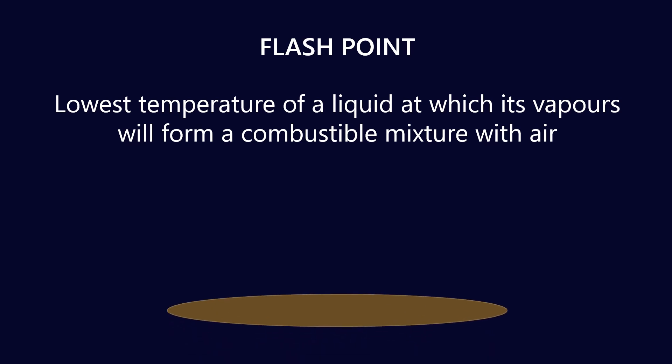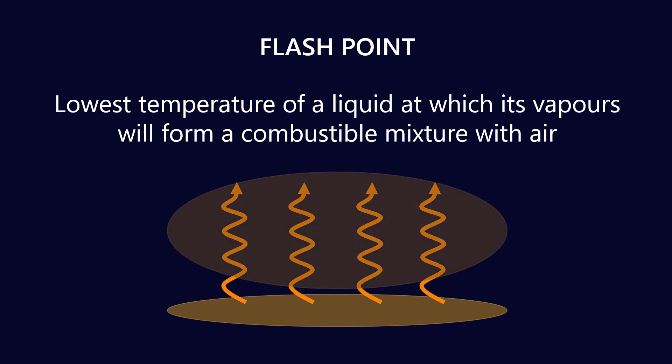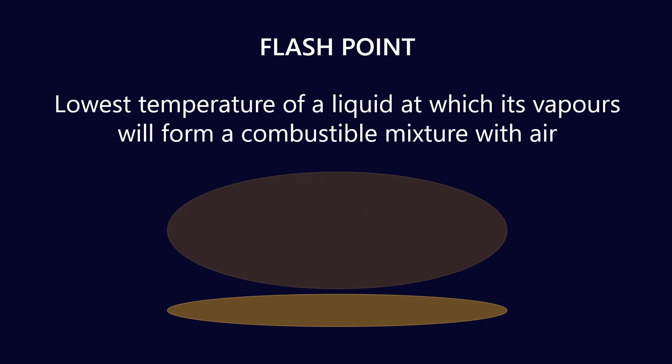Let's say I've got a pool of lubricant that's been spilled on the floor. Some of that is going to evaporate into the air — that's dependent on vapor pressure, which depends on the temperature of the fluid as well as ambient atmospheric pressure. As it volatilizes, a vapor cloud forms above the puddle. At some point, if you introduce a spark or a flame, it can ignite — and we would say the lubricant has reached its flashpoint.